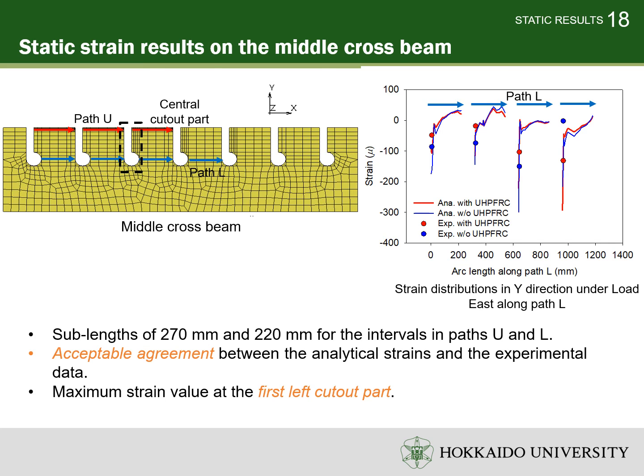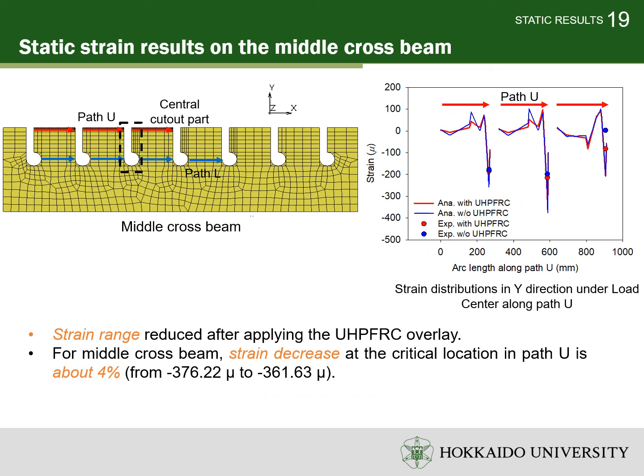It is found that most of the strain curves agree very well with the experimental data points. It can be seen that the strain distribution along path L changes sharply when approaching the edge of the circular cutout in the middle crossbeam, and the higher strain level is obtained from the first left cutout part. Similar to the strain result along path L, the strain level along path U near the rib to deck weld joint significantly increases when the strain curve approaches the cutout edge. The highest magnitude of strain is also obtained from the first left cutout.